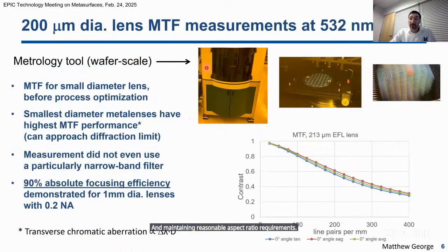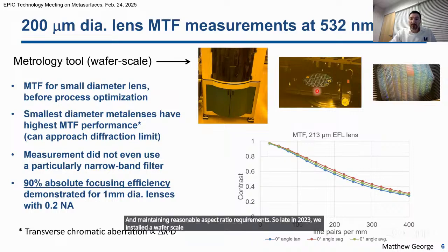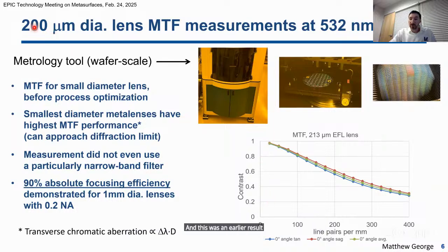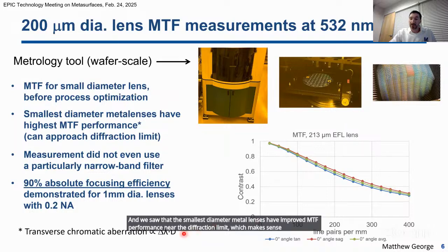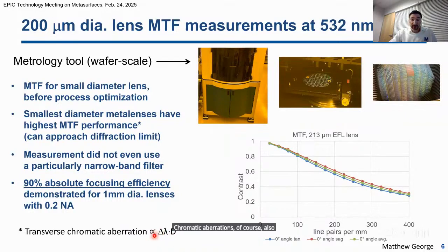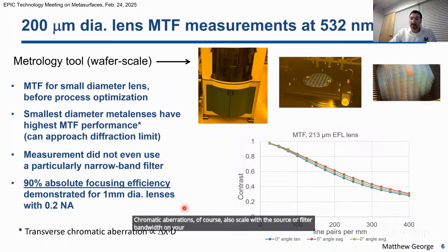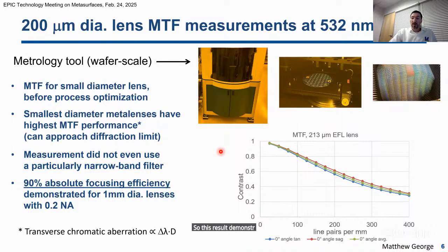So late in 2023, we installed a wafer scale metrology tool for MTF, focusing efficiency, and other meta-optic measurements. And this was an early result for a small 200 micron diameter Metalens before full process optimization. And we saw that these smallest diameter Metalenses have improved MTF performance near the diffraction limit, which makes sense since chromatic aberrations scale with lens diameter. Chromatic aberrations, of course, also scale with the source or filter bandwidth on your metrology tool. And these measurements didn't even utilize a particularly narrow bandwidth, which makes the measured MTF performance all the more impressive. So this result demonstrates the promising potential for applications utilizing small diameter metalenses.